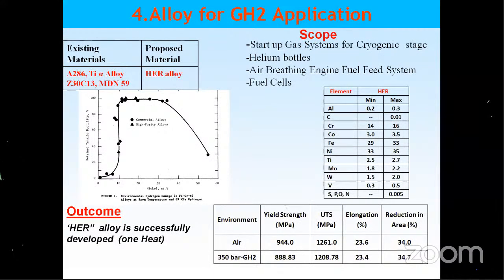Then about the hydrogen application, I made a material. There is a finding, the real reason of which has not been found out. If the nickel content of the steel is between this and this, your hydrogen environmental embrittlement is much lower. So we have developed an alloy, and it is made commercially. This is the composition. It is available in ISRO, and we named it HER alloy, hydrogen environment resistant alloy.